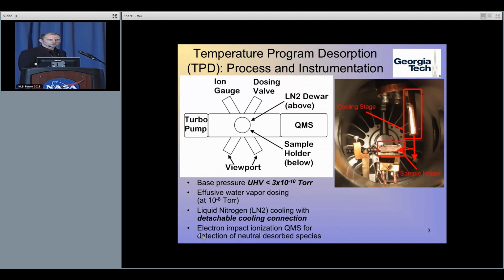To introduce the water to the samples, we use effusive water dosing, which basically means we flood the chamber to 10 to the -8 torr. And then we use liquid nitrogen for our cooling. This is sufficient for the majority of the lunar surface. One very unique thing we have in our chamber is a detachable cooling connection. This allows us to virtually eliminate all background signal, because when we get to the heating stage, we completely remove the cooling stage from the sample and we only heat the sample holder itself.